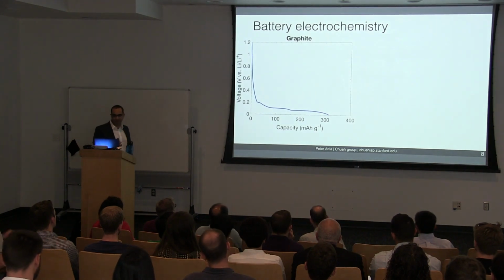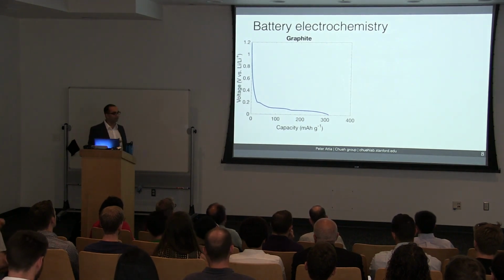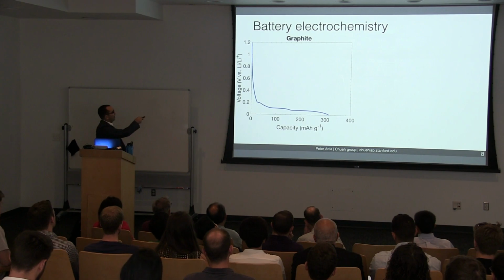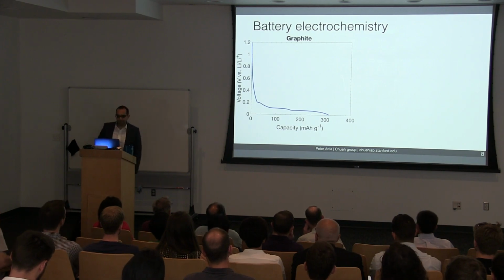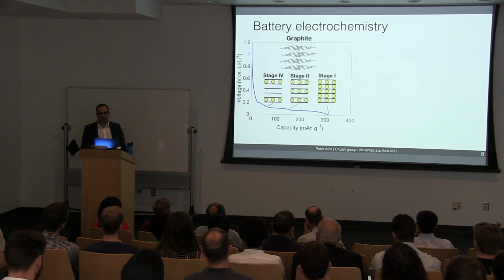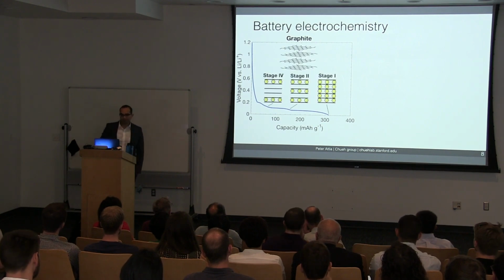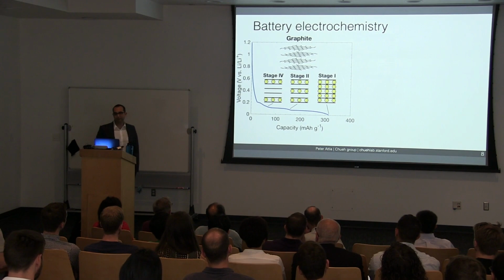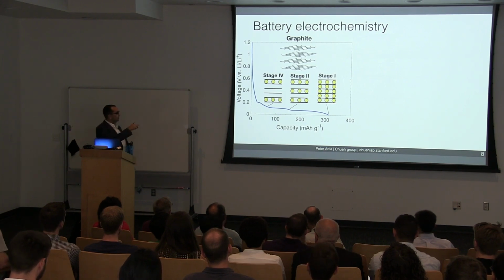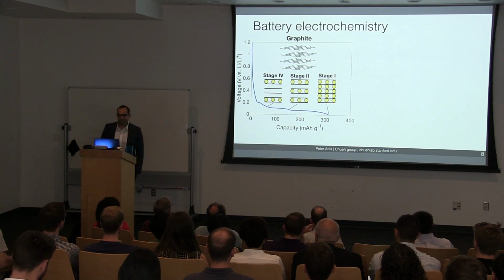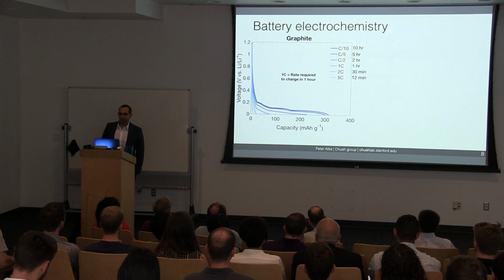Now, batteries are electrochemical devices, so electrochemistry is one of the key tools that I use in my work. This is a plot of voltage versus capacity for the graphite electrode. It basically plots the energy per lithium ion, which is the voltage, versus the number of lithium sites, which is the capacity. You'll notice that there are both steep parts of the curve as well as really flat parts. The flat parts are phase transitions between different lithium graphite phases. As we add more lithium to graphite, the lithium inserts into every fourth layer, then every second layer, and finally every layer. The plot I just showed is for 10-hour charging.